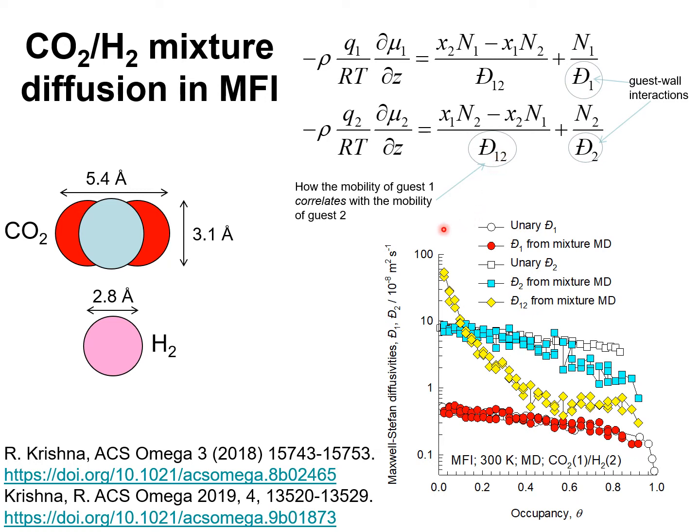We can use molecular dynamics to determine these diffusivities as explained in these publications, and the MD simulations for CO2 hydrogen mixtures are plotted against the pore occupancy in this diagram. The red circles represent the diffusivity D1 of CO2.